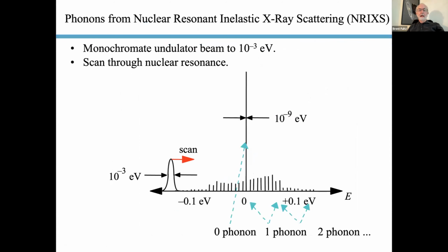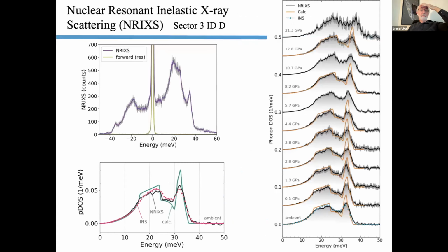I also won't go through how the monochromators work for doing the nuclear resonant inelastic X-ray scattering. It's a marvelous thing to explain to a general audience, but I don't think we need it here. But I'll show some data. Here's the INVAR data for room temperature on the upper left with an elastic peak here. But you can see nicely the cutoff of the 1 phonon scattering, the 2 phonon parts, and so on. Now, as I said, we're only looking at the iron 57. So the question is for the nuclear scattering, what are the nickels doing in the vibrational density of states?